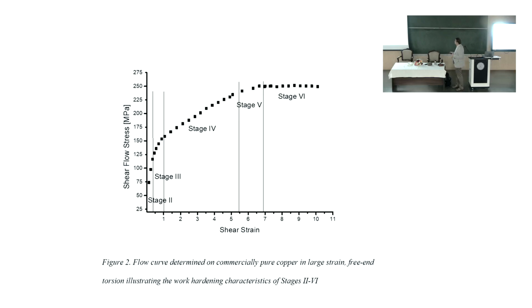So then when this more or less linear stage is finished, there is a transition stage up to a constant, steady state situation. And especially this stage is very fascinating because here we have constant stress, constant average grain size, and it goes forever. So you can just increase the strain, and the stress is not going to increase anymore, so strain hardening is finished.